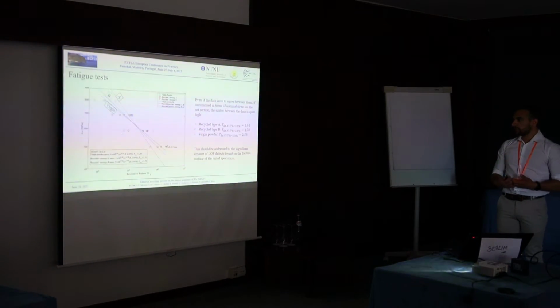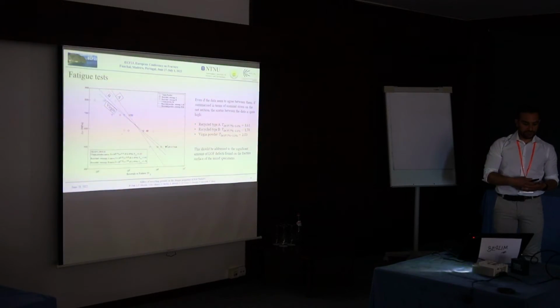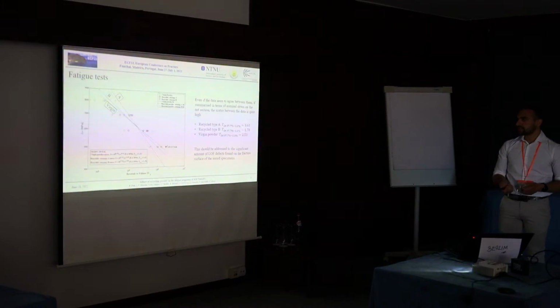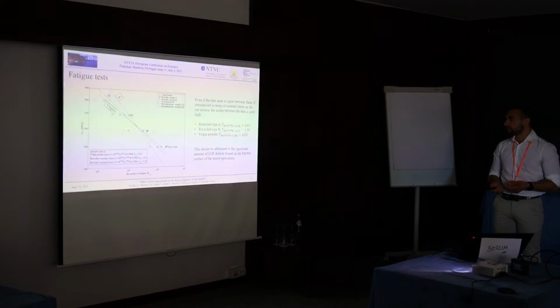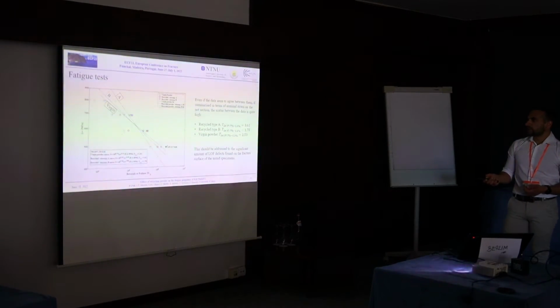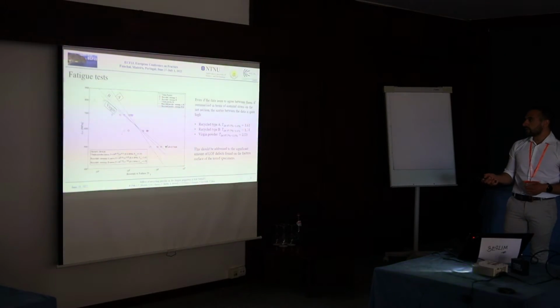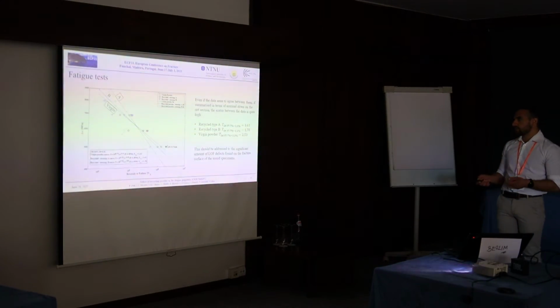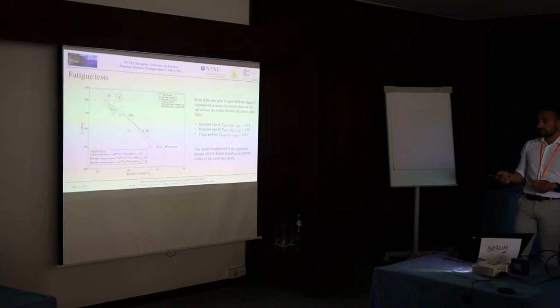First of all, we start by summarizing the results in terms of stress range on the nominal net section. As you can see here, the scatter of the results is quite high. In particular, if you consider the recycled type A strategy, that was the strategy considering powder recycled more than 100 times, the scatter of the data is quite high, as is the scatter of the virgin powder. This should be attributed to the significant amount of lack of fusion defects that we found on the fracture surface of the test specimens.